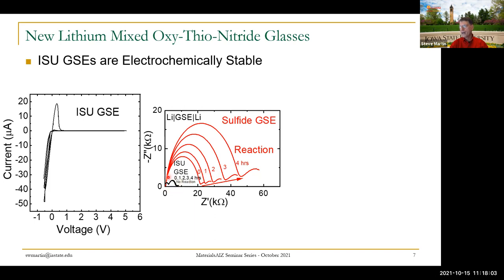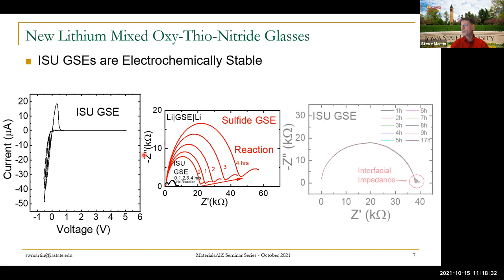This little diagram down here is our ISU oxysulfide glasses, and you can see two things. Their conductivity is higher, in other words, their resistance is lower. And then there's a little bit of width to these curves. There's a little bit of reaction, but clearly not very much, meaning that sandwich stays just the sandwich. There's no large interfacial impedances forming between the glass and the solid electrolyte, which of course we need for long-term stability. That's shown a little bit more here where I've blown this curve up a lot.